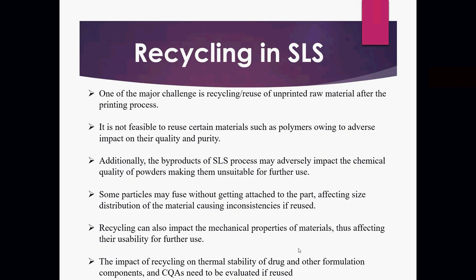So what would the people do? They are going to take 30% only from this recycled or unprinted raw material and mix it with 70% fresh powder, so they can avoid these recycling problems. We are going to study in detail in our next project how we can optimize the use of this recycled powder in SLS.